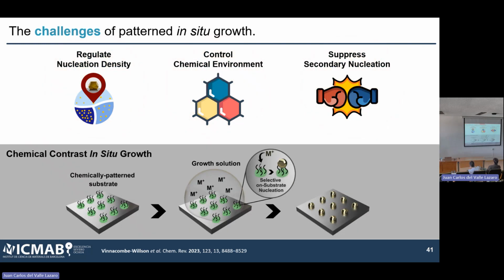And so the approach that we proposed, we called chemical contrast in situ growth. Basically, the idea is, let's use soft lithography, every technique that we learn in self-assembly. But instead of using it to assemble particles, we apply it to change the chemical composition of the substrate. So what we wanted to do is create a substrate with two different surface chemistries: one surface chemistry good for particle growth, the other bad for particle growth. I create this and then expose it to a growth solution. My particles will be able to nucleate and grow only at surface one. So theoretically, this is what I should get. All right. Again, this is the pretty picture.